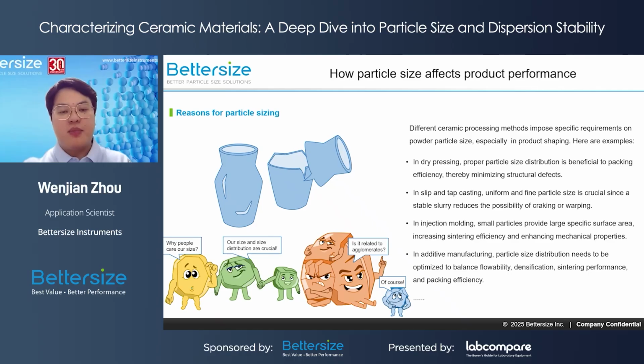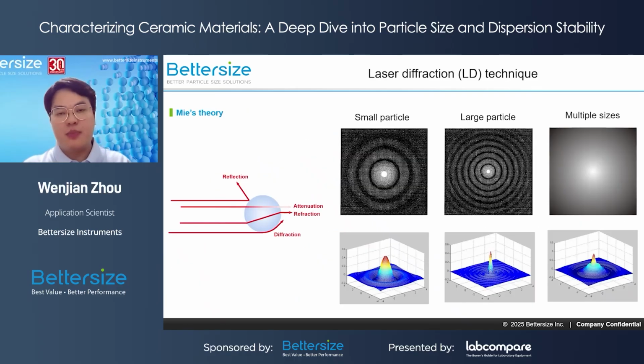In injection molding, powder and a binder are injected into mold. Particle size defines the flowability of the feedstock, the binding efficiency, sintering performance, and the mechanical strength of the final product. In general, smaller particles are usually preferred because they promote densification and thereby improve the product's performance. In 3D printing, particle size and distribution needs to be optimized to balance the flowability, densification, sintering performance, and packing efficiency. On the previous slide, we learned how particle size affects the manufacturing of ceramic product.